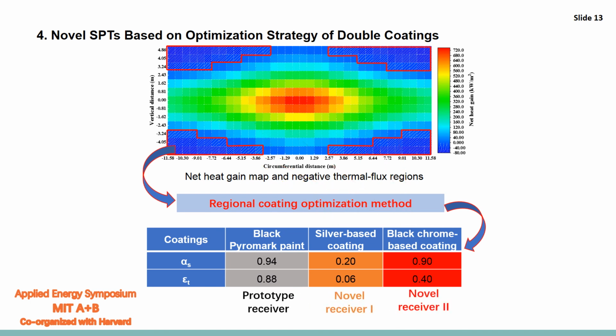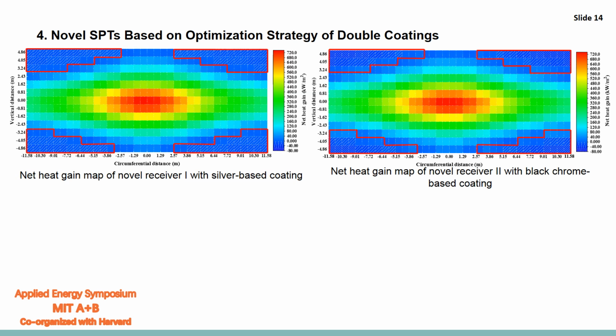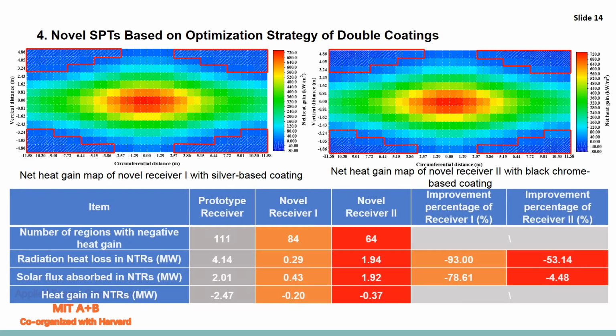Then we calculated the thermal performance of the novel receivers with silver-based coating and black chrome-based coating. The net heat gain maps of these two kinds of novel receivers are presented here. We can see that the number of the regions with negative heat gain is reduced to 84 and 64 in the novel receiver 1 and 2 compared with the prototype receiver. Correspondingly, the radiation heat loss in NTRs is significantly reduced by 93 and 53% because of the very low thermal emittance of the silver-based coating and the black chrome-based coating.